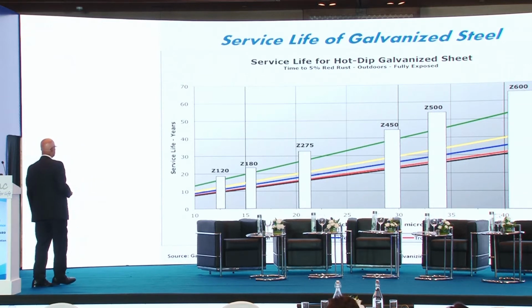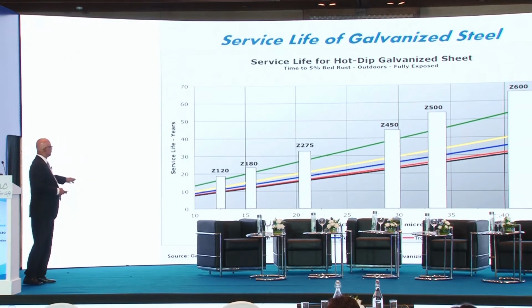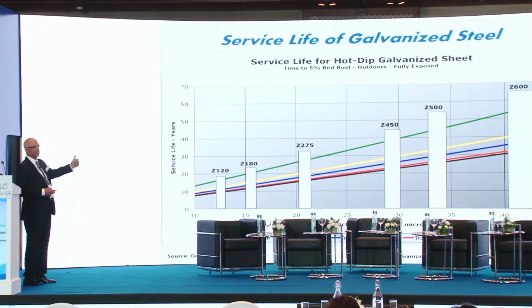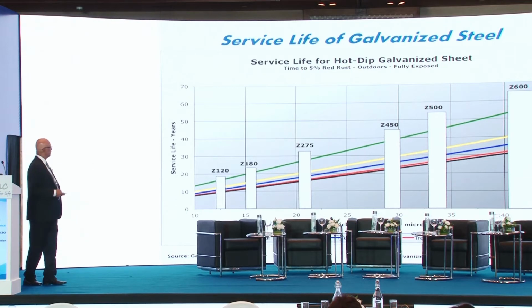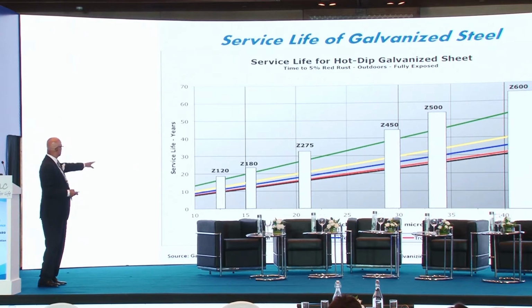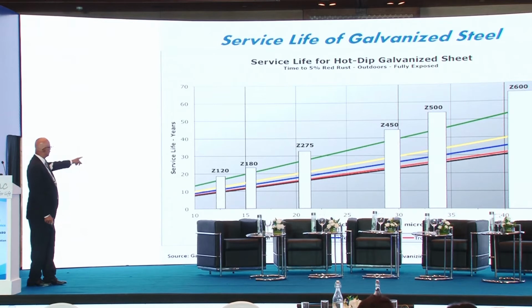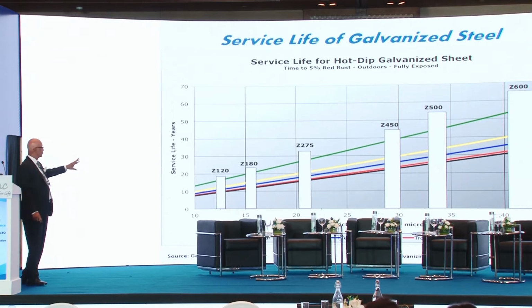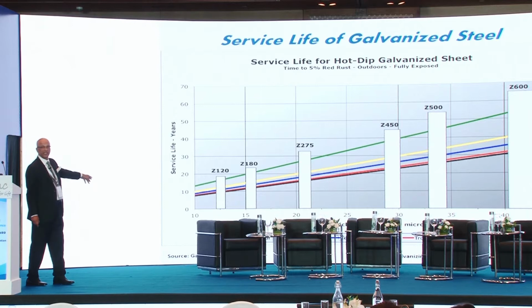So basically, depending on whether it's an industrial, which is the black line, or a rural, which is the green line, you can expect that type of service life over a period of time. So for example, the Z120, which is the total of both sides of 120, or 60 grams per side, will give you, in an industrial environment, less than 10 years.